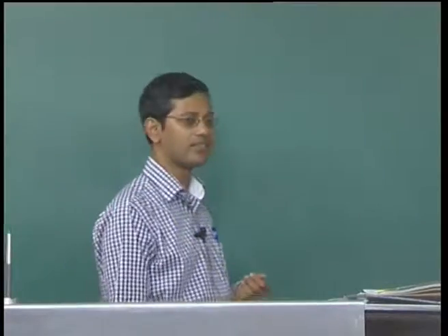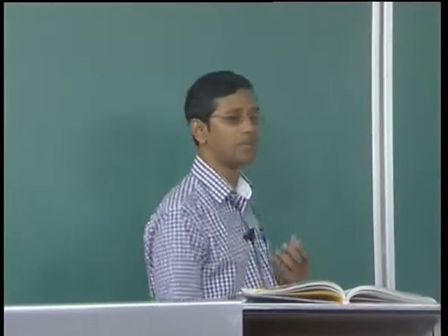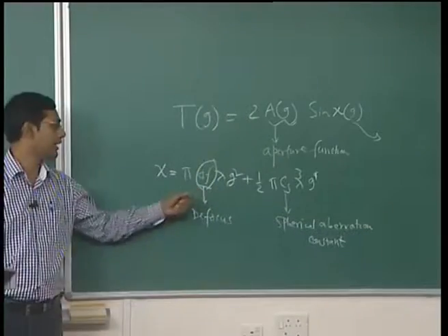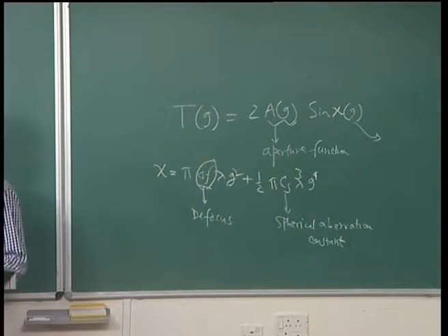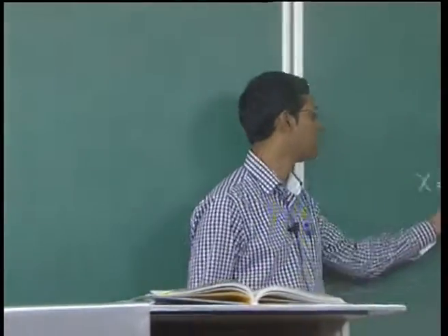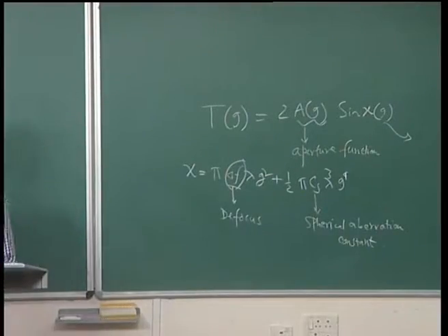So, knowing that Cs is fixed for a particular microscope, the free parameter which can play the important role is delta f, the defocus, and that is where we showed you how this function can change using different values of Cs and different values of defocus. So, we discussed this factor in detail and found out the optimum focus limit for high resolution microscopy.